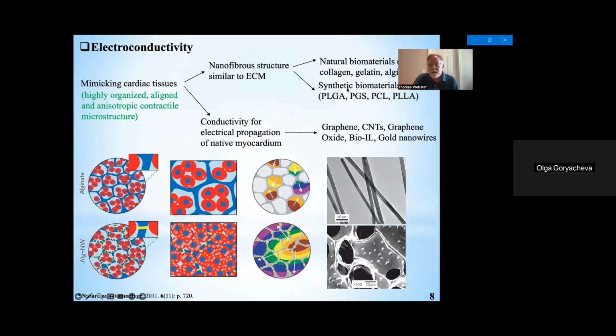So again, here are some of the materials we're using as the matrix, and here are some of the nanomaterials. CNT stands for carbon nanotubes that we're using and have used in these approaches. And I would be happy to highlight that what we're seeing is very versatile. As long as our material is conductive, graphene or carbon nanotubes, or even we have some research with gold nanowires, we can add it to a number of different matrices, gelatin, synthetic biomaterials. When we create linear patterns of these materials, we can induce anisotropic electrical properties, anisotropic mechanical properties, and get healthy regeneration of the heart tissue. That's what I'll show you.